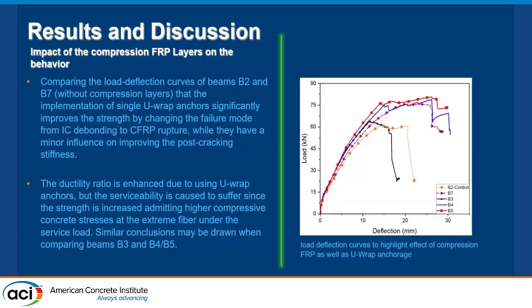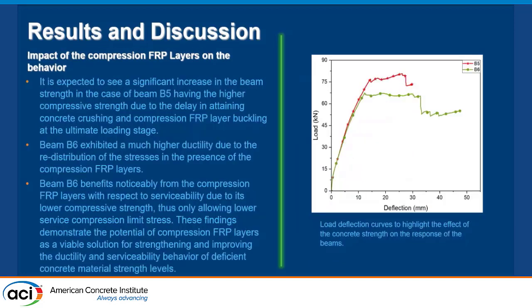The ductility ratio is enhanced due to using the U-wrap anchor, but the serviceability suffers since the strength is increased, admitting higher compressive concrete stress at the extreme fiber. A similar conclusion could be drawn for beam 3 and B4, 5. To see the impact of the FRP layer on the overall behavior, we have here B5 and B6.